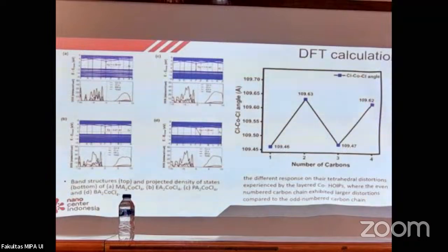And then, of course, you're going to need some DFT to back up your story. So we give you two conceptions here: the band structure, which gives you the band gap energy of the respective compounds. But the most important thing is just to give you an idea that they basically look the same. But if you look more closely, we have some interest in the conduction region. In the conduction region, the contribution from the p orbital slightly differs from the others. And this is the nice thing when you have very nice computation time: we can actually collect the information of the value of the bond angle.